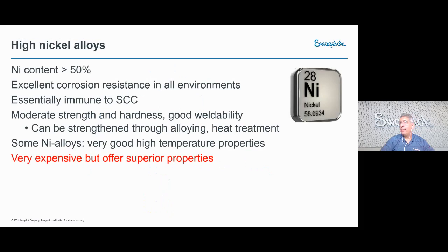So nickel-based alloys are more expensive, relatively immune to stress corrosion cracking, have much improved resistance to pitting and crevice corrosion than the iron-based stainless steels, and in many cases can handle higher strength and temperature resistance. So they're big workhorses for certain applications in and around chemical plants and refineries, as well as in the hotter sections of gas turbine engines too.